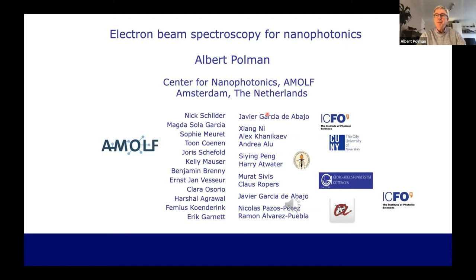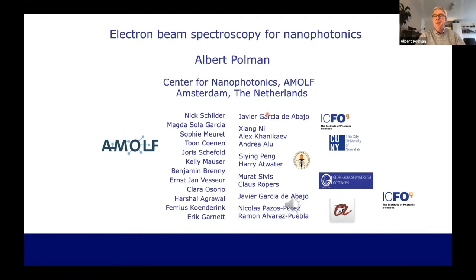I called this 'Electron Beam Spectroscopy for Nanophotonics' because what I'm going to introduce to you, if you're not so familiar with this, is how an electron beam is actually a fantastic source of optical excitations. In materials science, when we do optical spectroscopy, we use lasers with nice single frequencies focused down to the diffraction limit. But a moving electron — that moving electron point charge — is also effectively an oscillation of electric fields because of the movement of the electron. That can couple to materials and excite optical excitations and resonances.